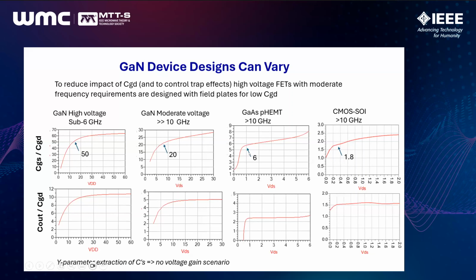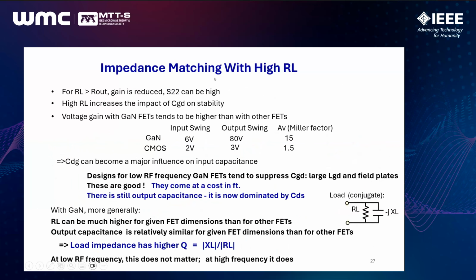In contrast, in gallium arsenide pHEMTs, the associated ratio of CGS to CGD might be 6. And in CMOS SOI with the symmetric digital-like structures, the ratio is 1. So these are good designs for low frequency, but they come at a cost in fT. There's still output capacitance, but it's now dominated by CDS rather than CGS.